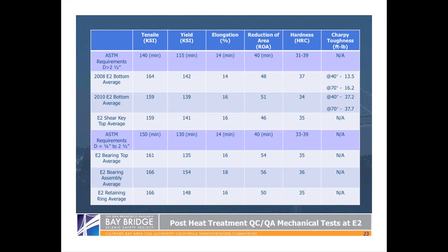This particular test, you do it at two different temperatures, because obviously steel gets more brittle when it's cold as opposed to being hot. And what you see are the values, in other words, the swing width, I'll call it. And you can see for the 2008 bolts, much lower values. For the 2010 bolts, much higher values.